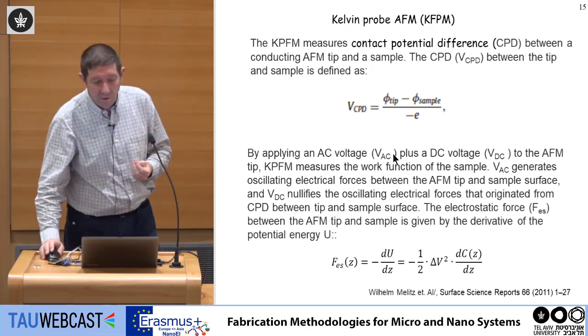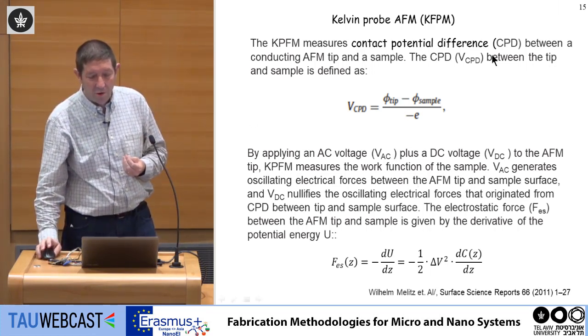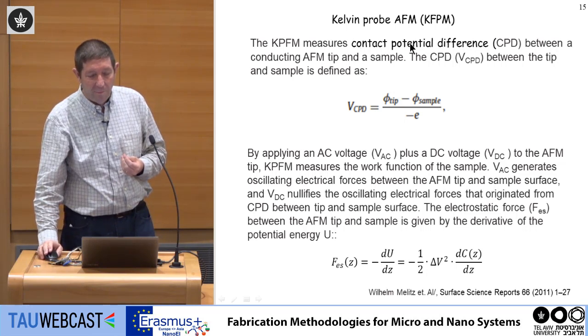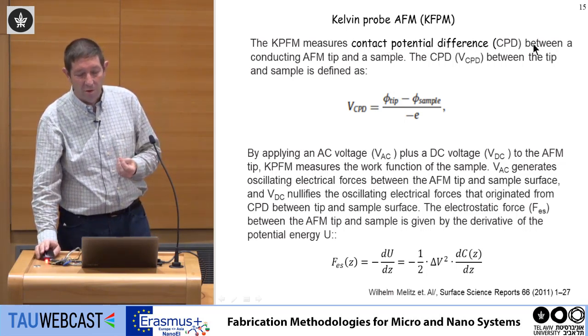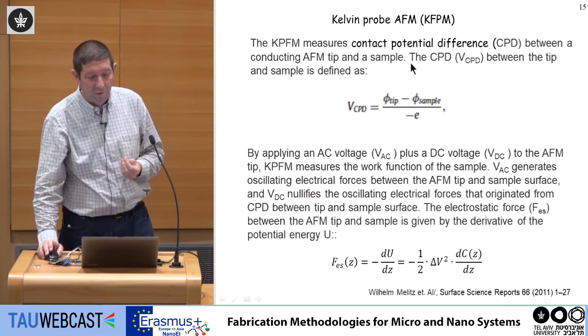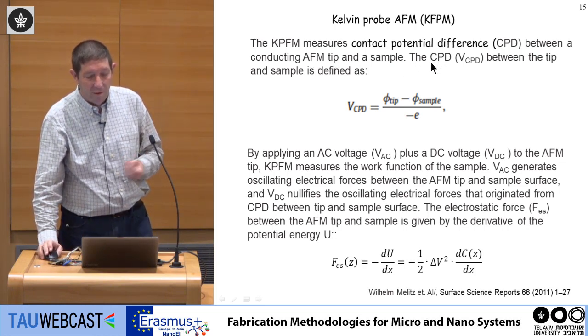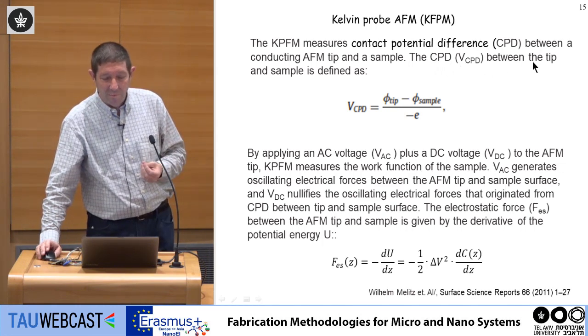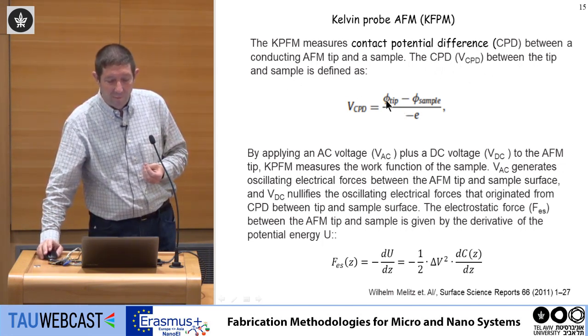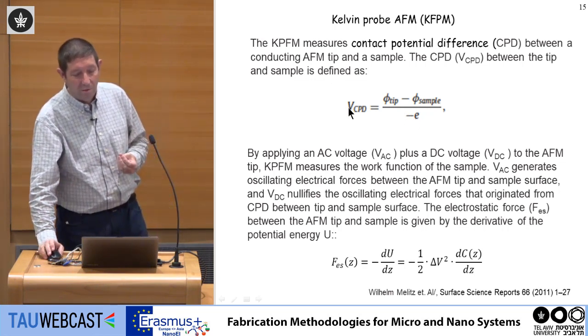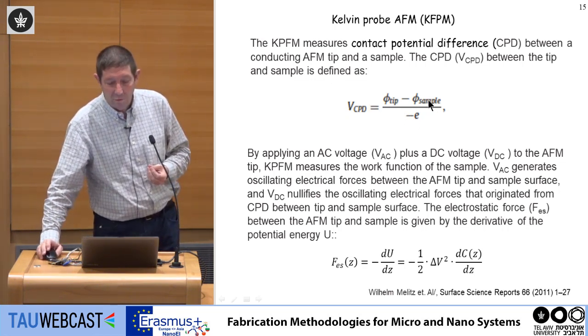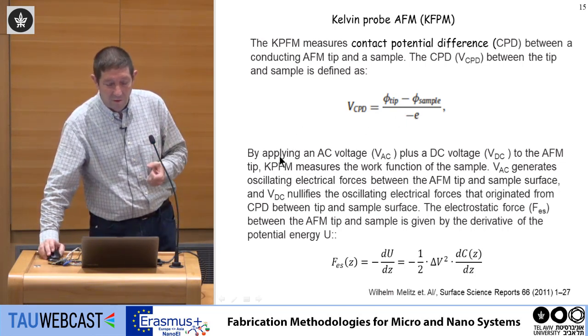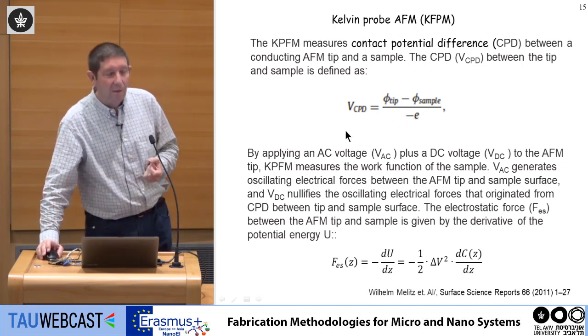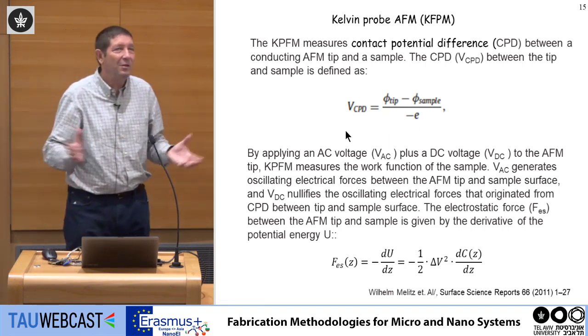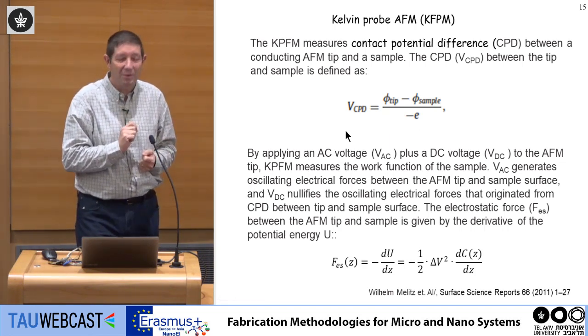Kelvin probe AFM measures the contact potential difference, CPD. The CPD, or VCPD, is the difference in potential between the conducting AFM tip and the sample. I just defined it with a q because I want the potential to be in volts, and this one I took in joules. So this is just notation. And then you can say, okay, this is good enough. But then we apply a trick here.